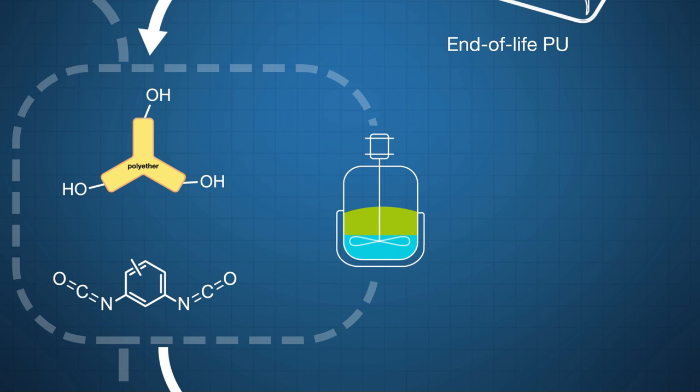After the reaction, a spontaneous phase separation occurs, allowing for the recovery of the apolar polyether polyol. A limited purification treatment is required to render the recovered polyether polyol suitable for the production of new flexible polyurethane foams.